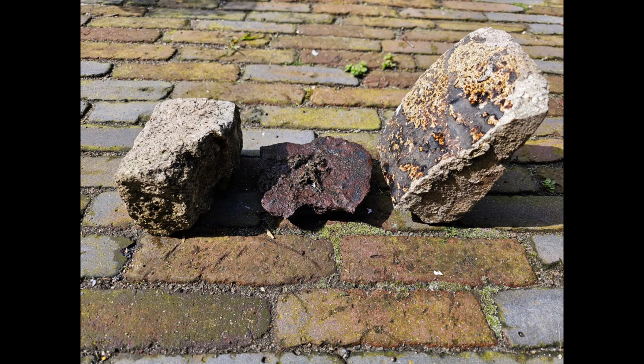This, in combination with the two types of slag that we see on the actual steel ingots, allows for the possibility that wood ash was used as a flux during the liquefaction process of these ingots. Hardwood ash is primarily comprised of calcium and potassium rich oxides and is therefore considered highly alkaline. Alkaline rich slags, particularly high in calcium and potassium, have the ability to absorb phosphorus in the form of calcium phosphate out of the iron and bind it to the slag. This will highly purify the iron in this case.